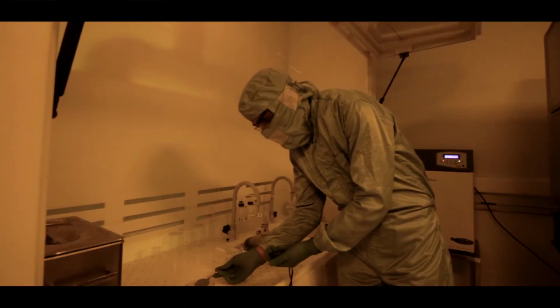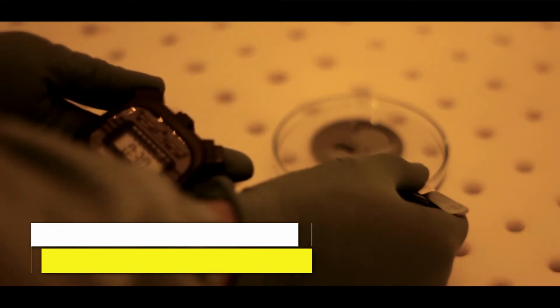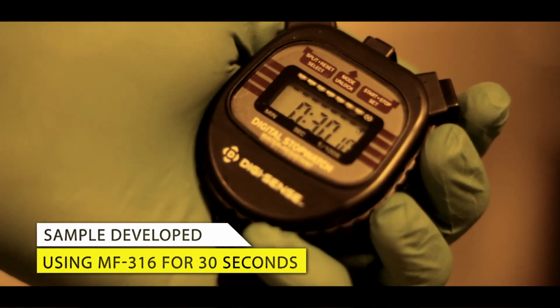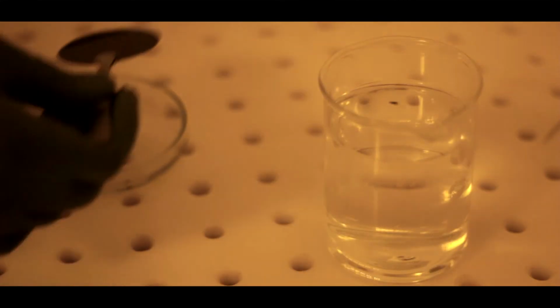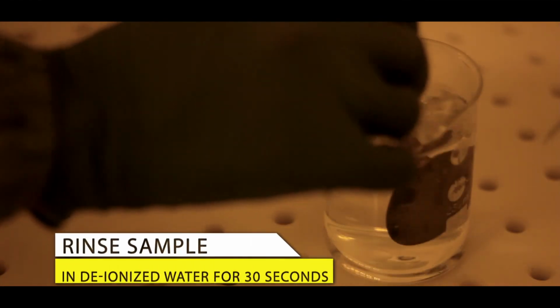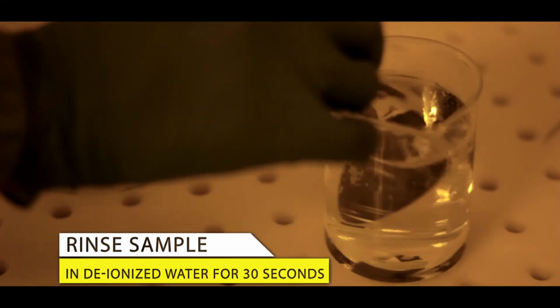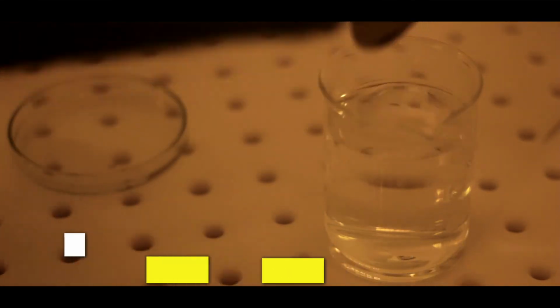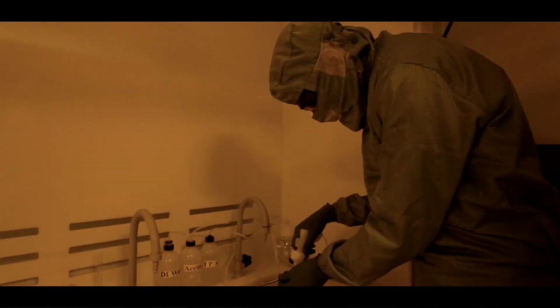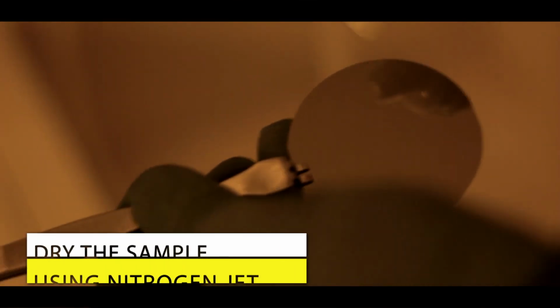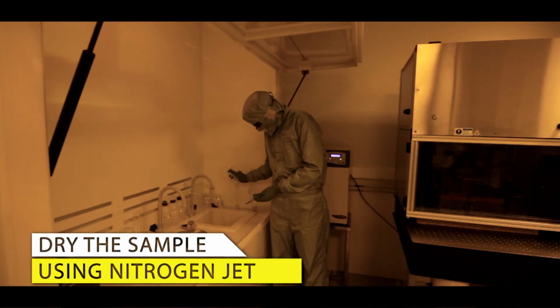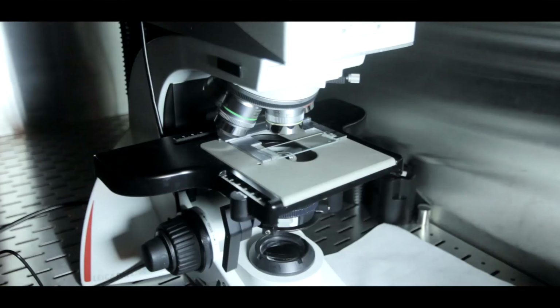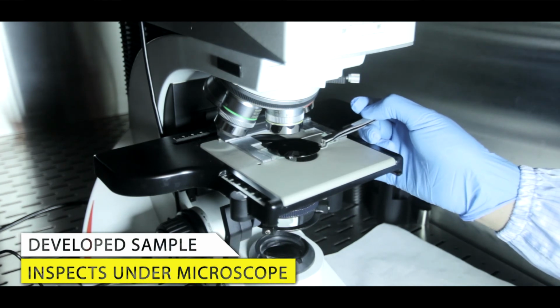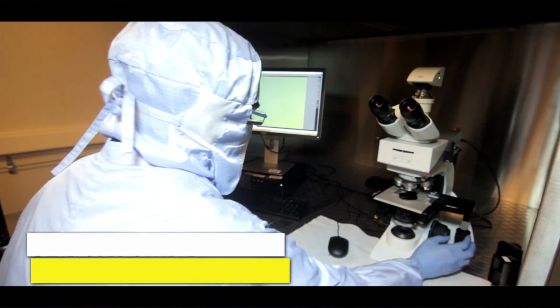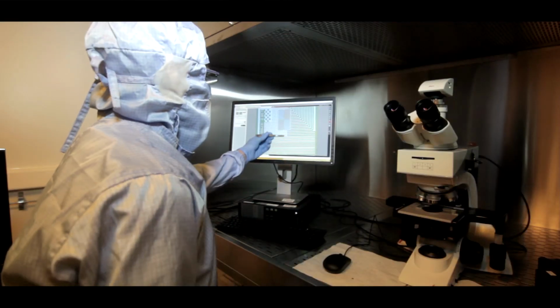Just after exposure, the sample is developed using MF316 developer for 30 seconds. After development, the sample is rinsed in DI water, followed by nitrogen dry. After development and nitrogen dry, the sample is inspected under the microscope. After exposure and development, the image clearly indicates the fine feature of 2 micron.